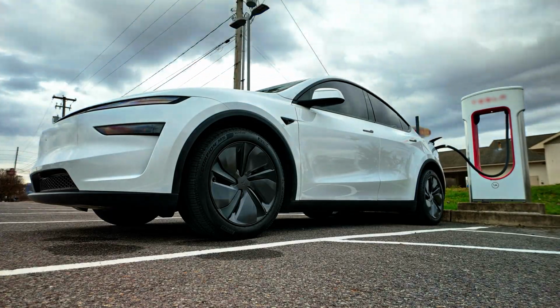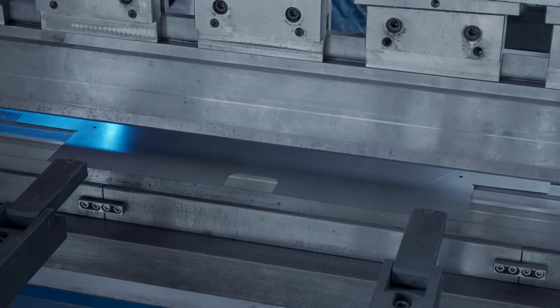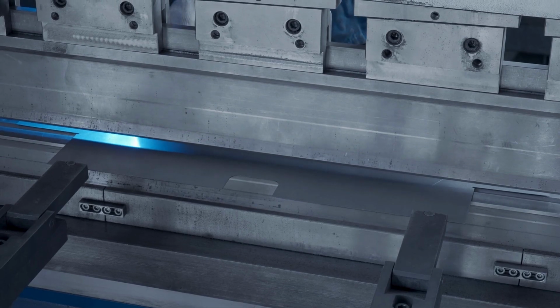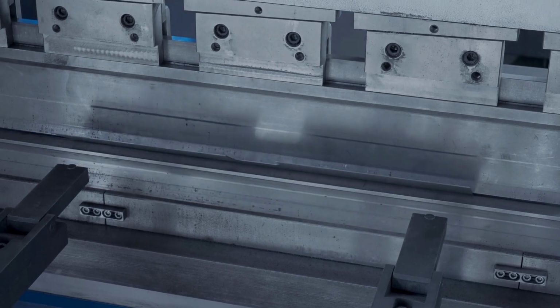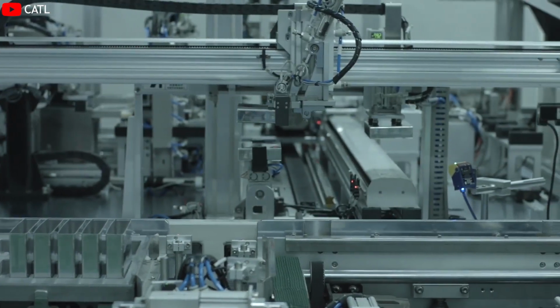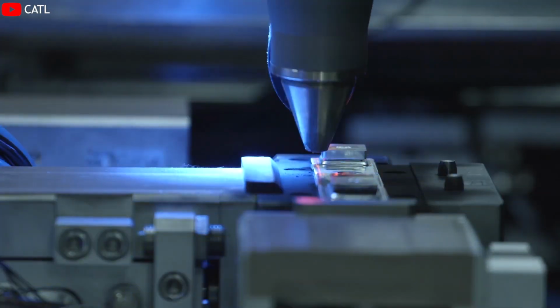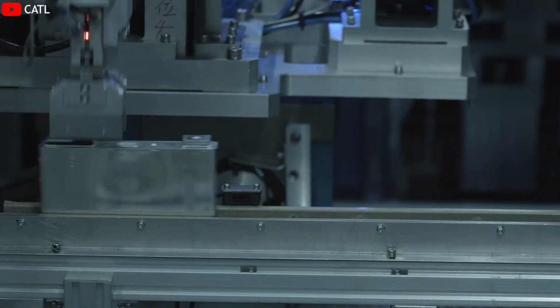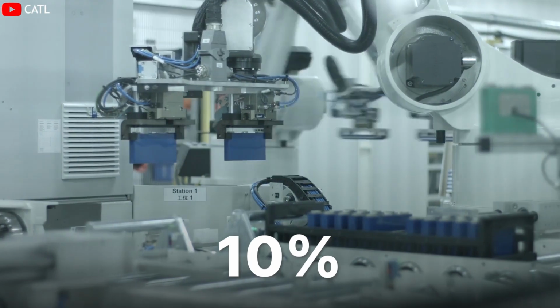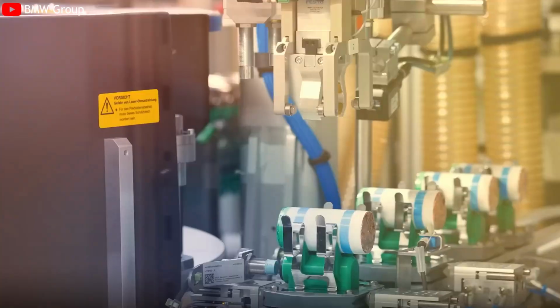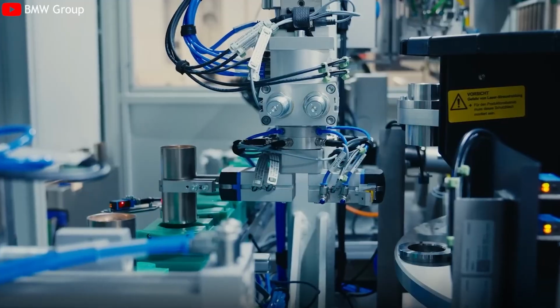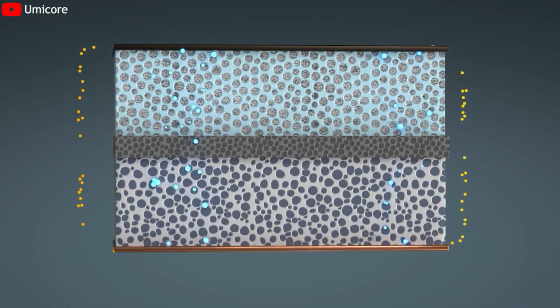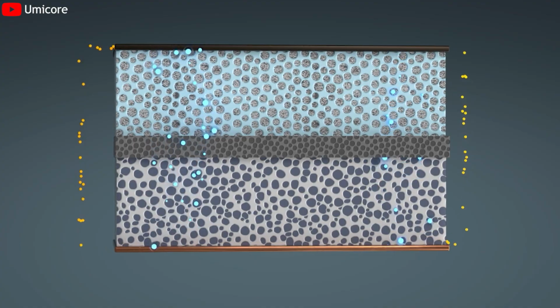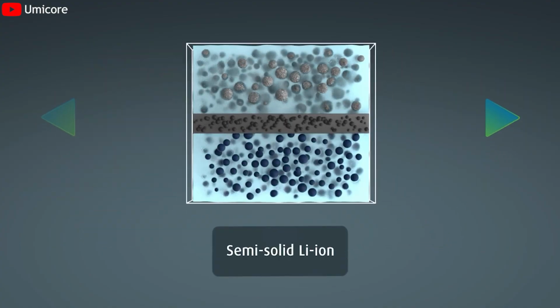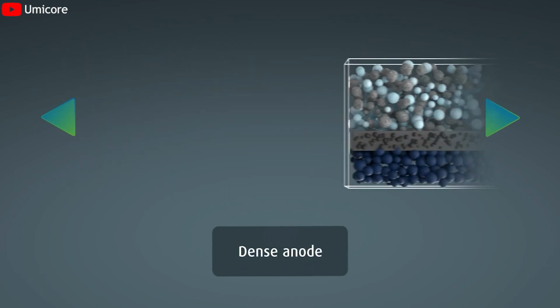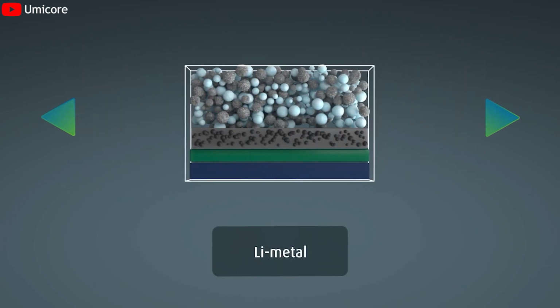That is not realistic. What happens when you force an object that expands by 300% inside a concrete box that cannot move? It destroys itself. A battery is a living, breathing organism. During charging, ions flood into the anode, causing it to swell. In conventional batteries, graphite expands by about 10%. The liquid electrolyte flows around this expansion like water around a moving ship. It adapts effortlessly. Solid-state batteries are not forgiving. They use high-capacity anodes like silicon, which expands by 300%, or lithium metal, which represents infinite expansion as the layer grows from 0 to tens of microns.